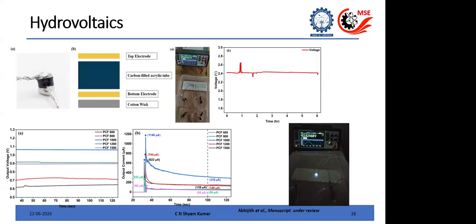So basically, now the sample is more graphitic, right? There is no nickel and all, but it is more graphitic because you have increased the temperature. Now, what we observe is that the maximum performance, if you look at the voltage and current, is not happening for the sample which is at 600 or at 1500, because it is happening somewhere in between, which is the sample which is heated to 1000 degrees Celsius. Now, here is the thing that I want to show, because now the trend is something different. Initially, the piezoresistivity was reducing with increasing graphitic content, but the EMI shielding was increasing with increasing graphitic content. But in this case, the best performance is happening somewhere in the middle.